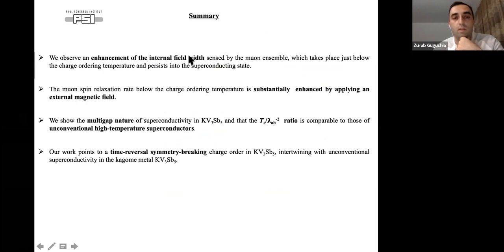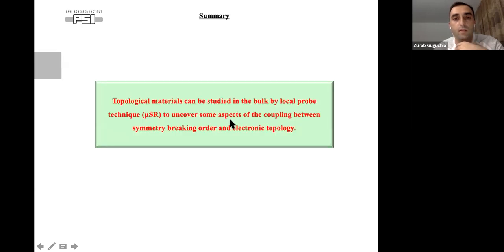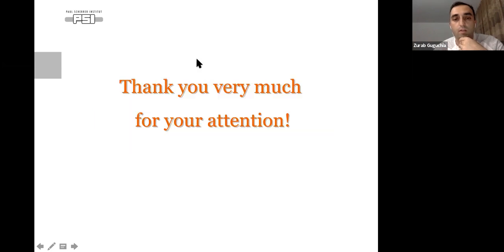So what we observed is enhancement of the internal field widths, as sensed by the muon ensemble, which takes place just below the charge density wave transition temperature. We see that we can enhance the electronic relaxation rate by magnetic field. We show that we have multi-gap nature of superconductivity with a small superfluid density comparable to unconventional high-temperature superconductors. And we conclude that we have time-reversal symmetry breaking charge order, which is intertwined with unconventional superconductivity in this material. So basically the general summary would be that I tried to convince you that topological materials can be studied in the bulk by local probe techniques to uncover some aspects of coupling between the symmetry breaking order and electronic topology. I'd like to thank you very much for your attention, and I'm happy to accept any questions.